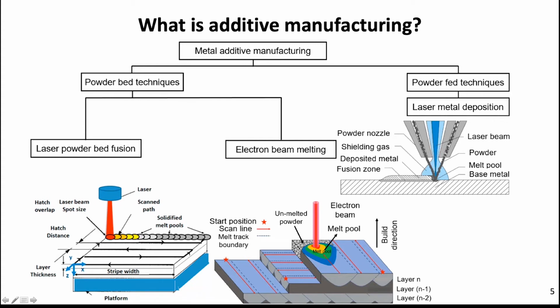Rather than having a laser, an electron beam could be used. This uses more energy and it produces larger melt pools typically. In contrast with this, there are the powder fed techniques, where powders can be fed, and these powders are of different composition. This is very useful to functionally grade components that have different compositions.